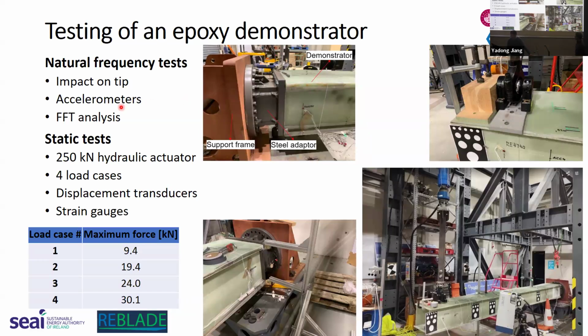And secondly, after we complete the natural frequency test, we apply a vertical load at the tip to push the demonstrator down, and this will give us the responses of the displacements and strain on the composite structure. Based on this data, we can analyze the structural performance of this demonstrator. So this is the whole test setup.